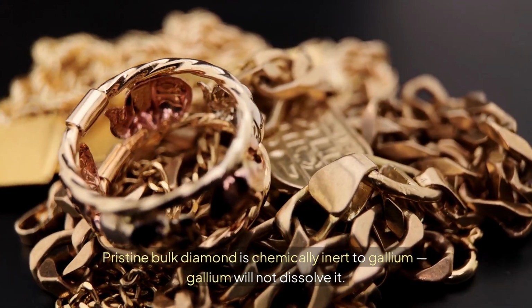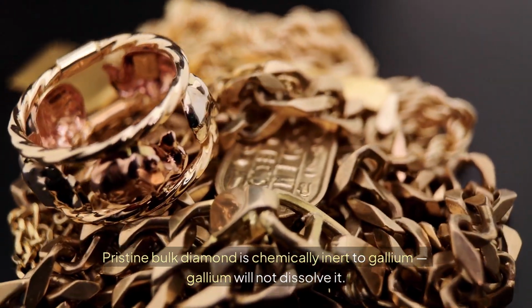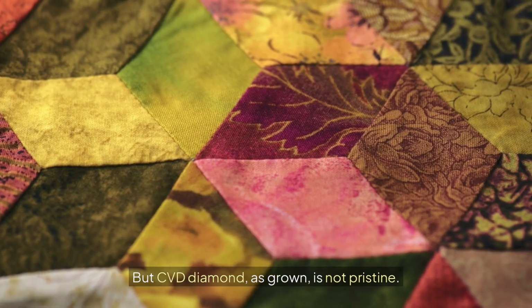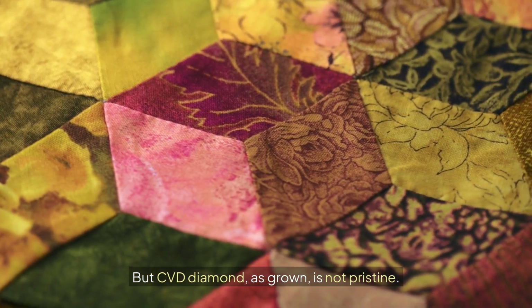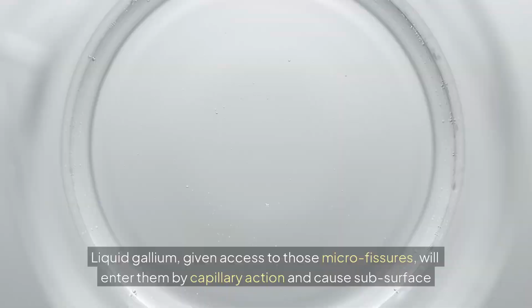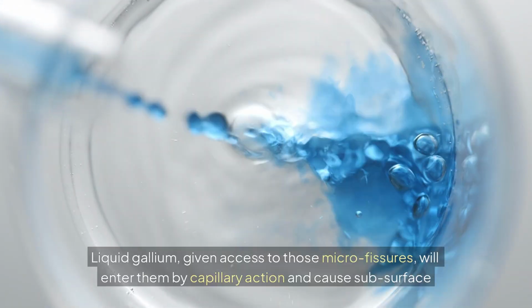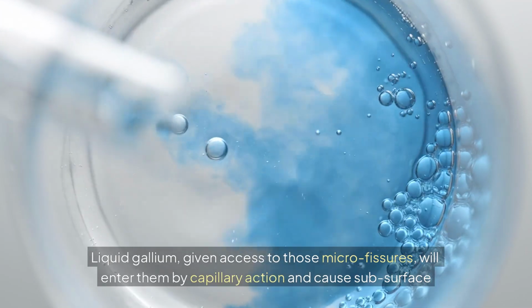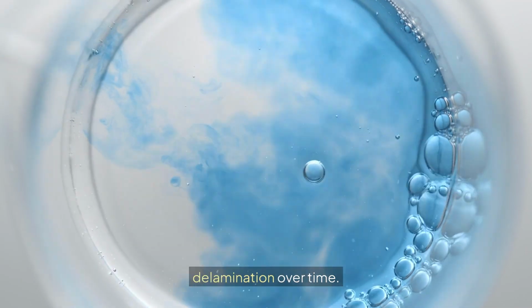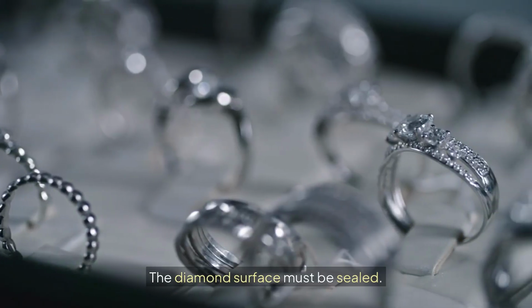Pristine bulk diamond is chemically inert to gallium. Gallium will not dissolve it. But CVD diamond, as grown, is not pristine. It contains grain boundaries, amorphous carbon phases, and microscopic void defects from the plasma growth process. Liquid gallium, given access to those microfissures, will enter them by capillary action and cause subsurface delamination over time. The diamond surface must be sealed.